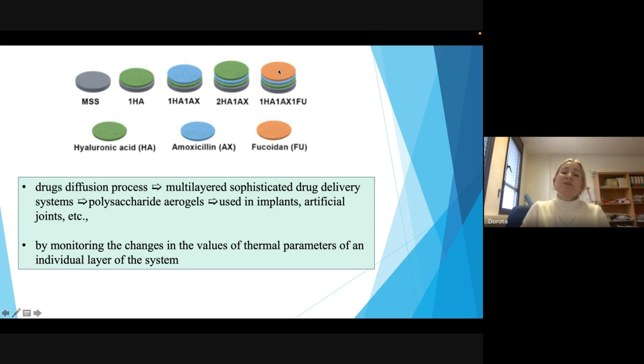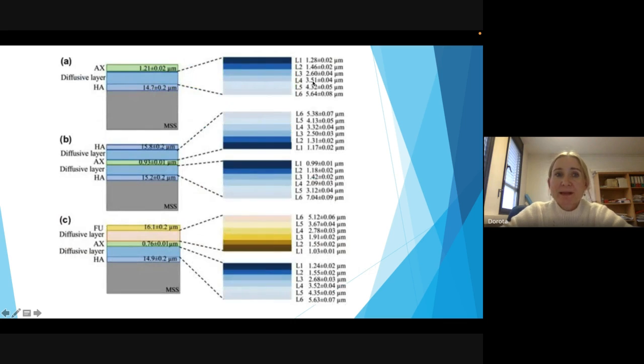We would like to see how the amoxicillin diffuses inside the upper and lower layers by monitoring the changes in the thermal properties. In the case of two layers, we built our theoretical model assuming that a diffusive layer exists between hyaluronic acid and amoxicillin. In the case of the three-layered samples, we have two diffusive layers, upper and lower part. So here and here is the diffusive layer. The same applies when the upper layer is fucoidan.